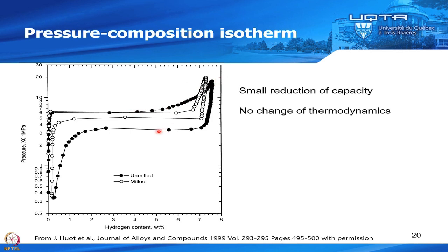But as we saw, when you do ball milling and you get a nanocrystalline structure, the kinetics is much faster, and you see that your plateau now is flat, okay? Because the kinetics is faster, and also this plateau moves up to here. So the hysteresis is much less. And you could see here for the unmilled one, that it starts to bend here, but the kinetics is so slow that it doesn't reach the equilibrium point. Okay, so this is why this plateau is lower. So this is not due to thermodynamics, this is due only to kinetics.